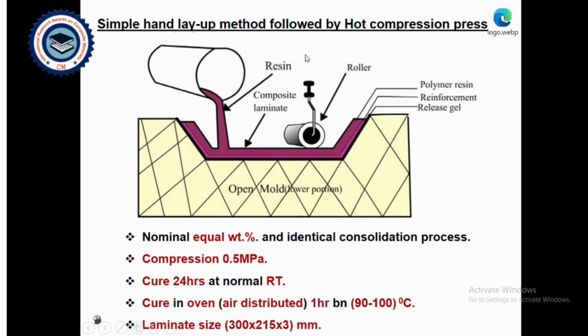We used the simple hand lay-up method in order to obtain the required fabricated composite material, followed by the hot compression press, with nominal equal weight percentage and identical consolidation process for all six types of carbon fiber composites. Compression used was 0.5 megapascal, cured 24 hours at normal room temperature, then cured in an air-circulated oven for 1 hour between 90 to 100 degrees. Laminate size was 300 by 215 by 3 millimeters.